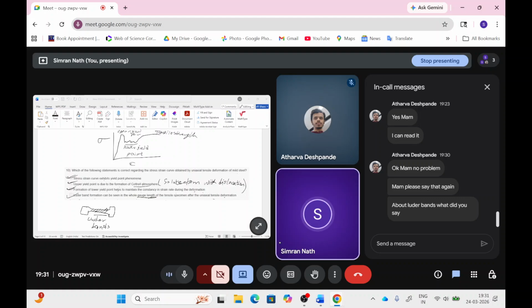The dislocation lines are formed at a 45-degree angle on the tensile specimen gauge length, and these dislocation lines in a group are called Luder bands.